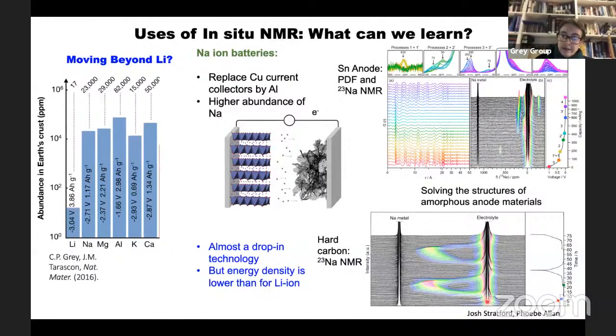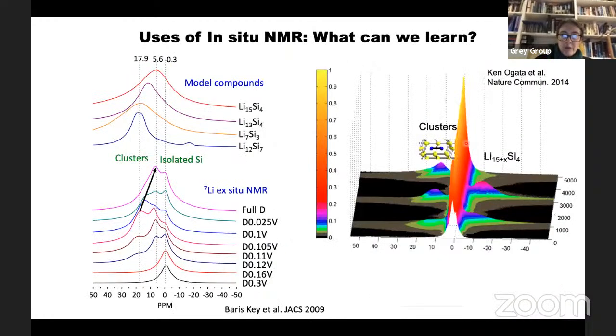What you can see here is two types of signal. One is around 0 ppm, and then you get this very large shift to more positive ppms, getting close to the signal of sodium metal. From this very simple experiment, we were able to prove that this low voltage process was due to sodium sitting in the pores of this material, forming so-called sodium metallic pools that gave you this metallic signal. So by doing these experiments, we can really understand not only the structures, but also the electronic structures of these materials.